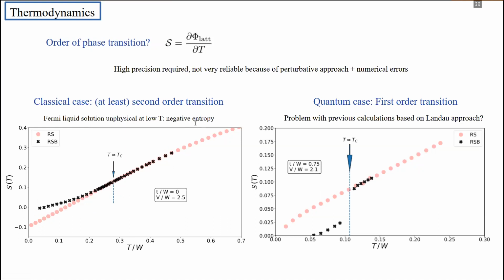And this entropy is completely continuous at the phase transition, which is here, showing that the phase transition is at least of second order. Now we switch on the hopping on the right-hand side and basically do the same thing. And here we get something very different. So these crosses tend to show that at the critical point, we see a jump in the entropy. So this figure would suggest a first order phase transition.